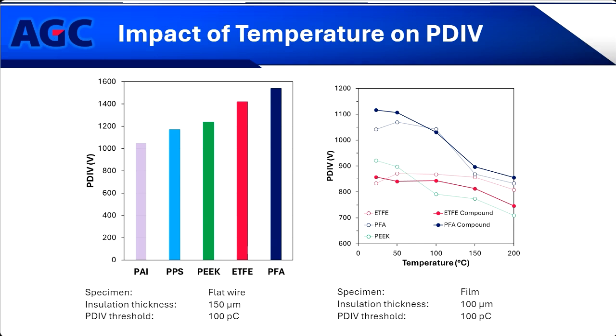Our PDIV threshold was the same, but one thing I want to note, as I mentioned about the way this test is performed, these tests were performed on a different instrument. So you'll notice that our maximum PDIV for our PFA material on the graph on the left is almost 1,600 volts, whereas on the right, it's only around 1,100 volts. Another thing to consider there is the type of sample we were testing, a film versus the wire, as well as the insulation thickness. Typically, as you decrease the thickness, your PDIV will go down. So just another good example of why understanding how the materials were measured is very important for this test.